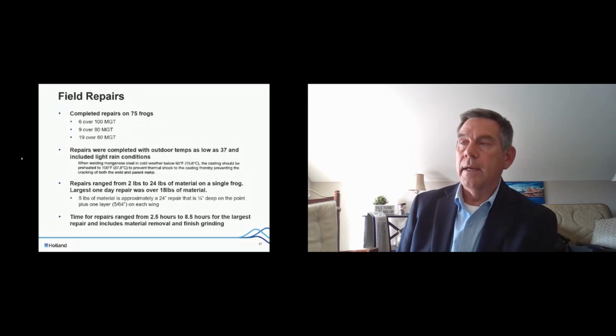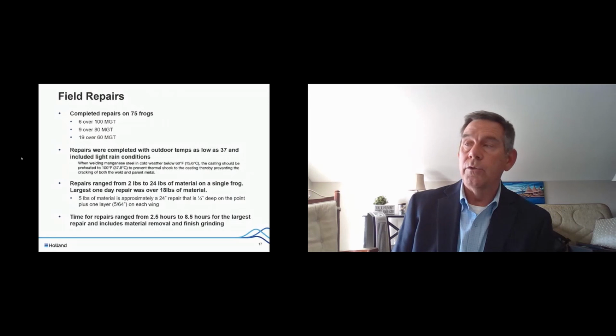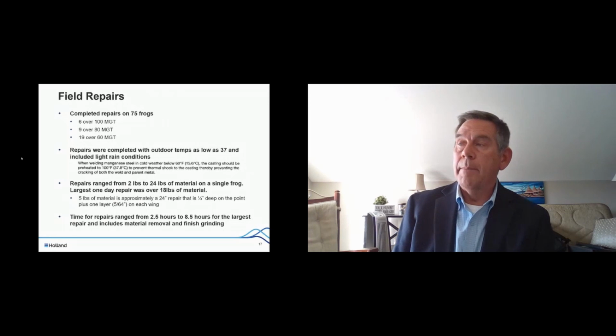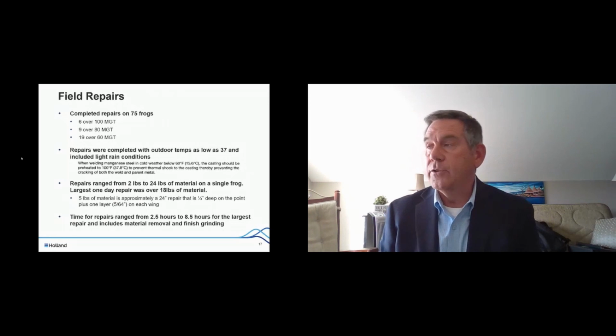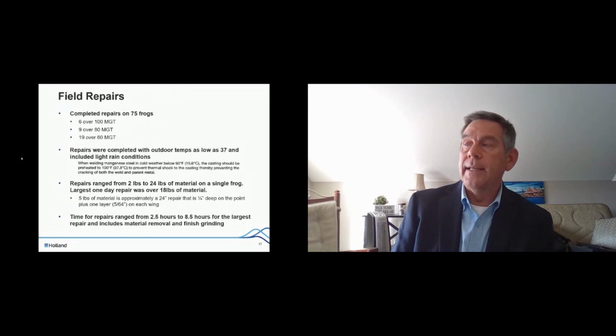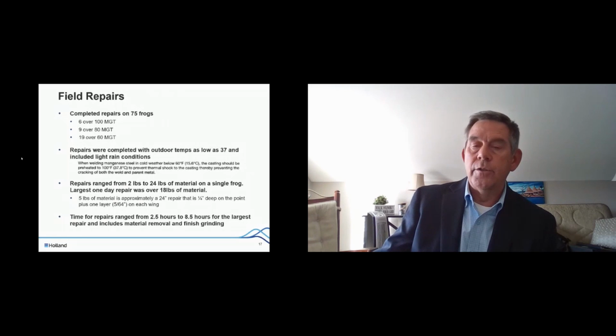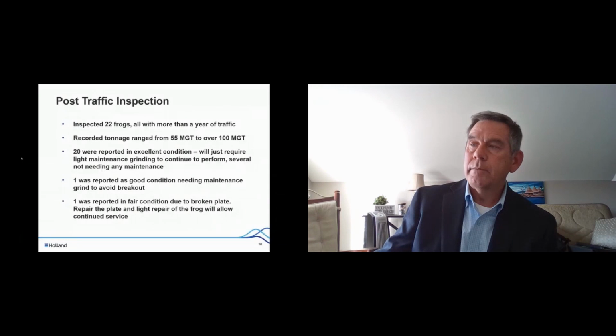Recently, in the last month, we inspected 22 of those repairs. All have more than a year of traffic and service life now. Recorded MGT was anywhere from 55 to 100. Almost all of them were in excellent condition. The only 2 that were in fair or good condition were because there are other underlying issues with the installation.